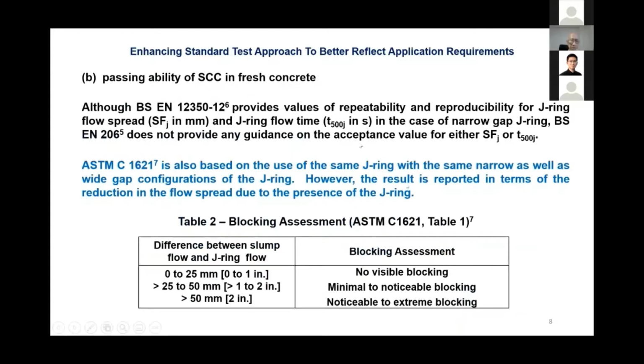Now, in the ASTM, they chose an alternate method of doing it, which actually was pioneered by us in NUS. We look at the flow diameter rather than the height. That means the flow without the ring and the flow with the ring. And we call that a passing index. Now in ASTM, for practice, that is too detailed. In research, it's very good. We'll show you later. But in practice, they want a simple rule.